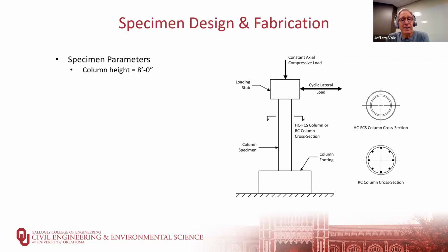Our column we selected in terms of what would work in our lab, we have a column height of 8 feet. That's from the top of the footing to the application point of the cyclic lateral load. The FRP outer diameter, we're essentially testing half scale columns. And we wanted to be in the range of 18 to 24 inches. We chose 18 inches, and because of standard sizes, that gave us an FRP pipe or tube of 18 5/8 of an inch diameter and a thickness of 3/16 of an inch.